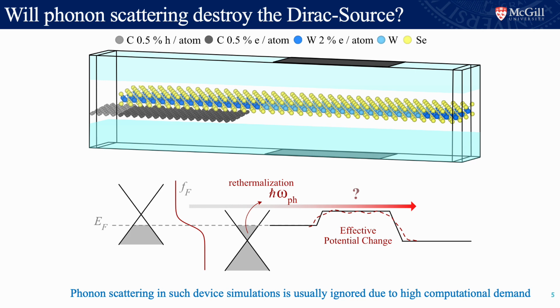However, the origin of the steep-slope switching remains controversial. Theoretically, the steep-slope switching is due to this p-type graphene Dirac source, because the density of states decreases linearly when approaching the Dirac cone. Ideally, electrons preserve their coldness before reaching the top of the barrier. An n-type graphene is usually applied to lower the Schottky barrier height. Researchers question whether inelastic scattering in this n-type graphene-semiconductor heterostructure will destroy the cold Dirac source and rethermalize the electrons.